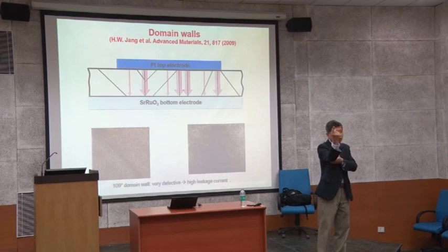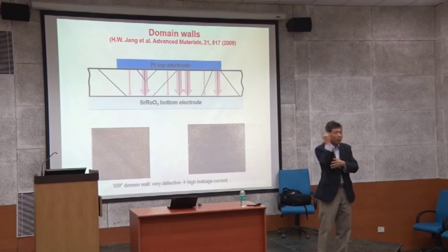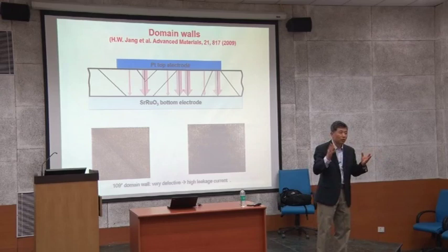And this one to that one, 180. So the angle we are talking about is not a measurement of it. It's actually looking at the possible combination of this polarization and other polarization. That angle relationship is 71 if it is a bulk case. But if there is some kind of strain, then 71 can be 69 degrees or something.